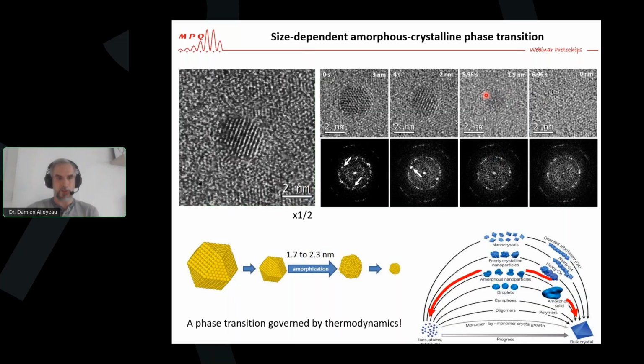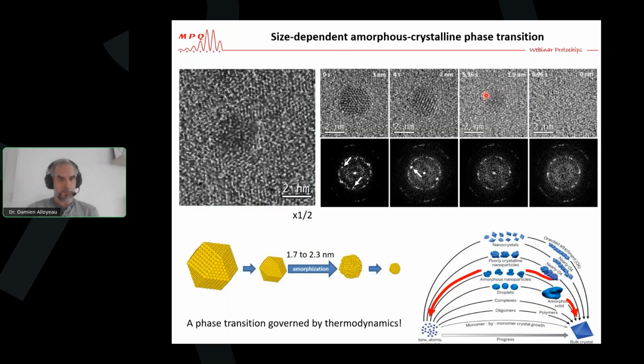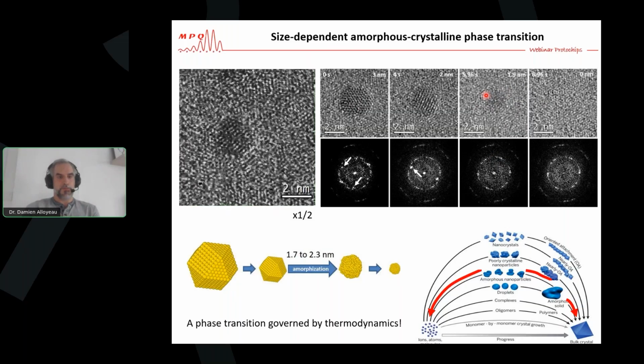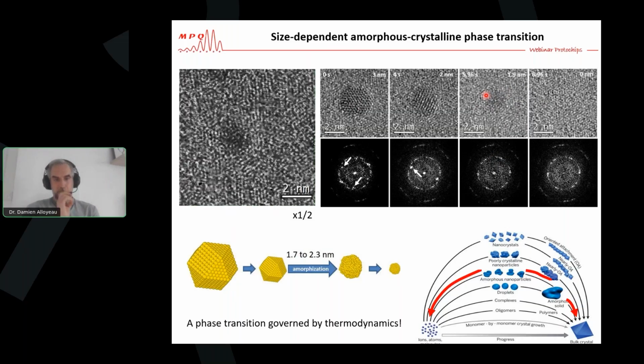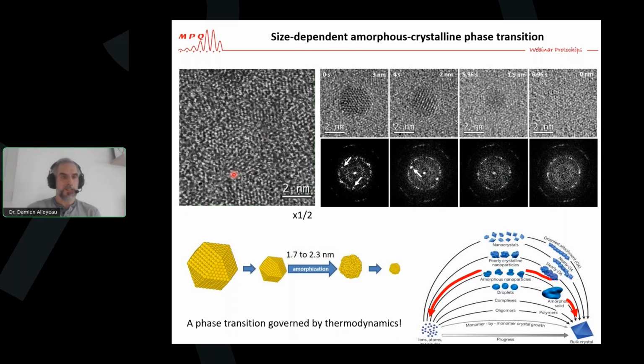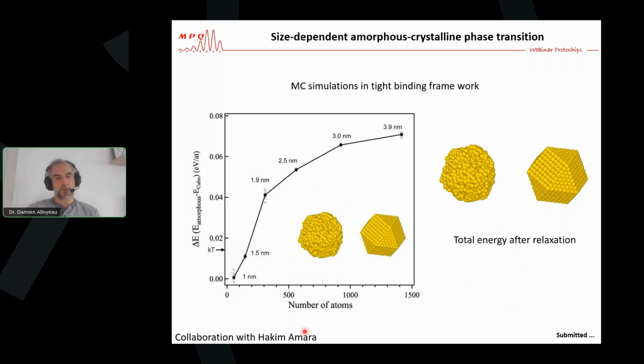It means that you have a thermodynamic equilibrium when the nanoparticle is below 1.7 nanometers. It's favorable to have this amorphous phase. And to confirm this result, we again collaborated with Hakim Amara, who has performed some Monte Carlo simulation in a